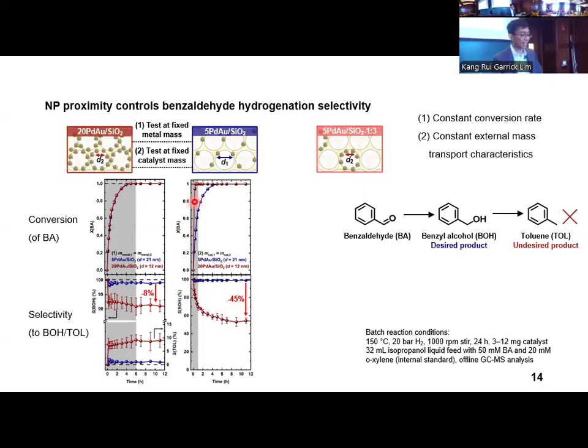Next, we tested catalysts using a fixed amount of catalyst mass. Unsurprisingly, the 20 weight percent catalyst in maroon over here showed a high activity due to its higher metal mass. But the effect of interparticle distance on nanoparticle proximity, on catalytic selectivity, was now even more pronounced.